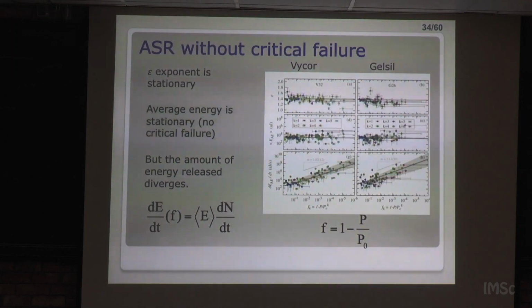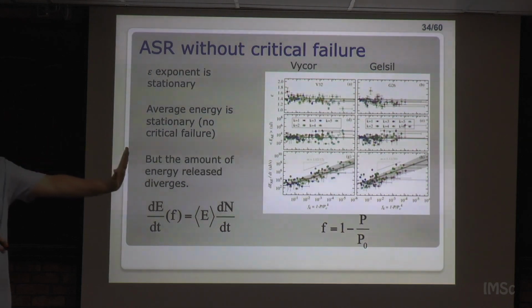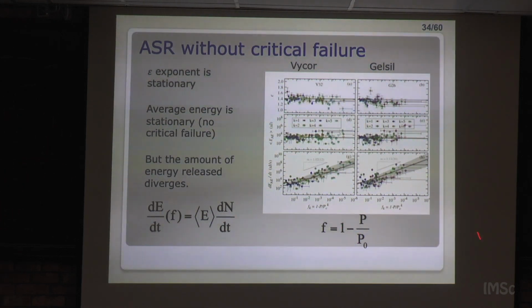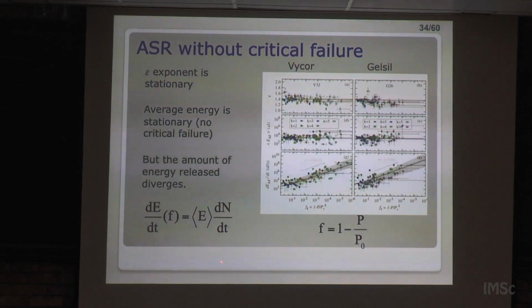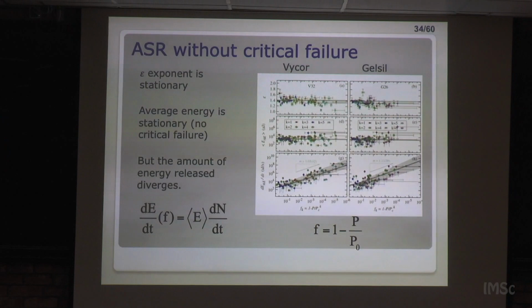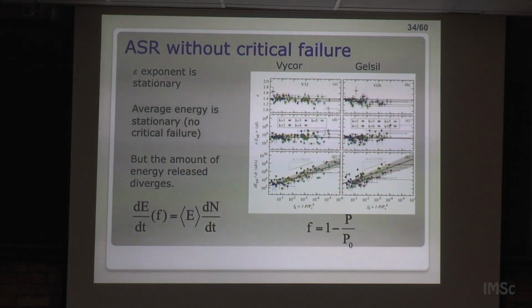And then what you find is that this is measured as the distance to the big event, in pressure. So it's the pressure minus the pressure of the big failure, divided by the pressure of the big failure, so it is normalized. You see that the exponent is still stationary towards that. I know that there are models that don't say that. The average energy is stationary, so this suggests that the distribution is also stationary, but what is different is the total energy release. Why? Because the energy release as a function of this force is the average energy times the number of events, and this is what is increasing. Essentially, you have an increase of the activity, not of the distribution of energies. Not the exponent, just the activity. This is what you find in this kind of samples. And this is for Vycor, and this is for Gelsil.